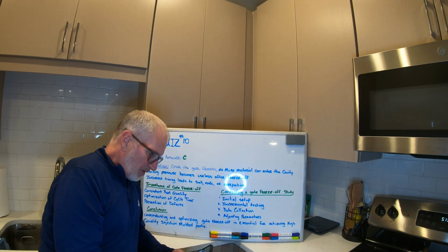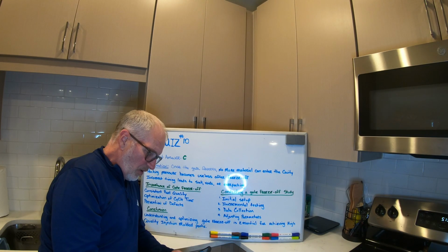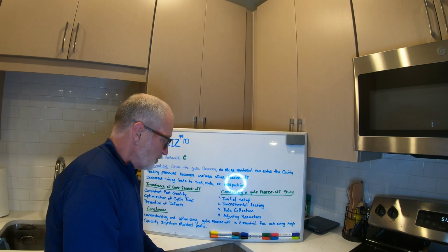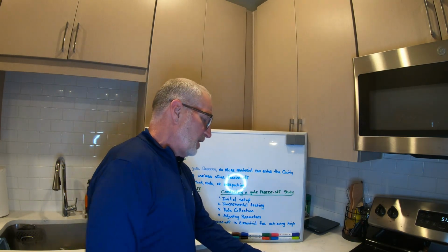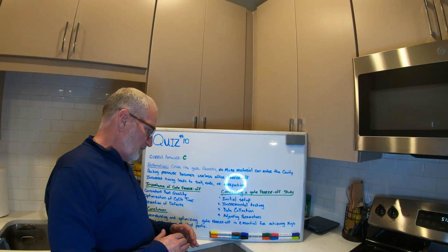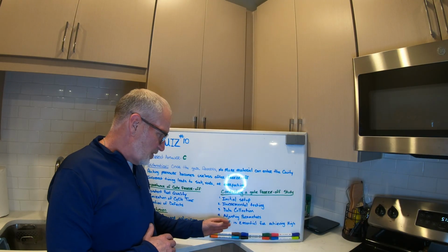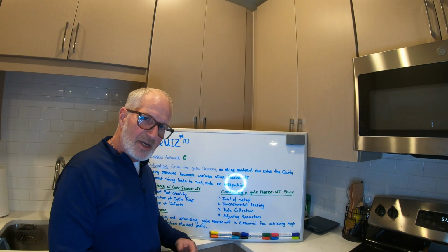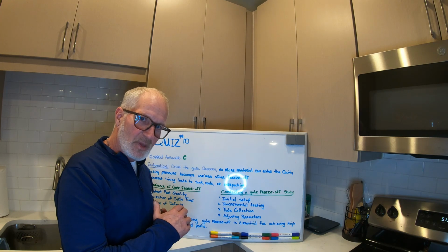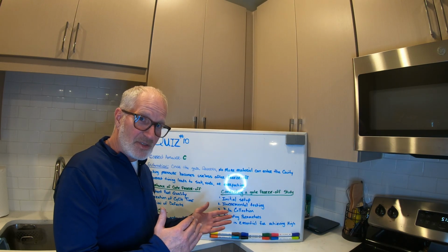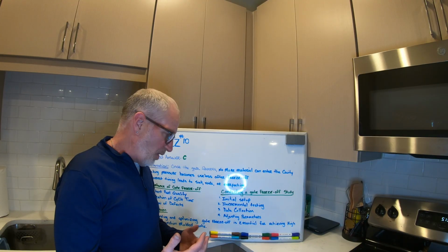So adjusting the parameters, the last one: based on the findings, adjust the hold time to ensure that it is slightly longer than the freeze-off time and account for any variations in the process. Let's say you get this to 5 seconds of hold time. Then you're going to add 1 more second to your hold time to make it 6 seconds. You might be able to add maybe half a second. It just depends on your part and all that.